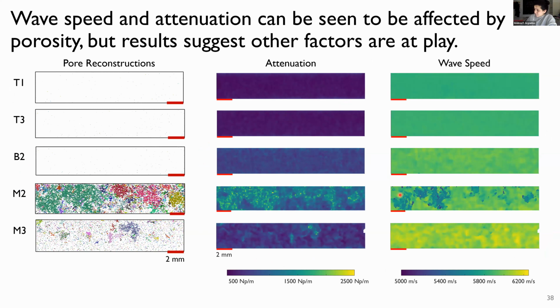The first three samples in terms of mapping are obviously not going to show us anything that interesting because the pores were isolated and small. So sure, you see some variation in this, especially in the wave speed that I'll talk about in a second. But other than that, nothing too interesting. That said, when we move to the samples that had these large pore networks, then you see some spatial correlation in where the pore networks were and the responses that we're seeing both in the wave speed and attenuation. So we wanted to make that a little bit more quantitative.